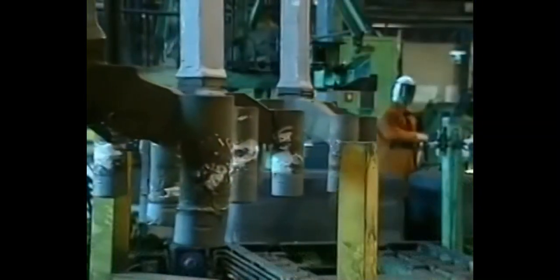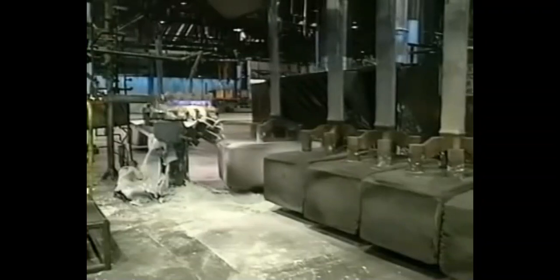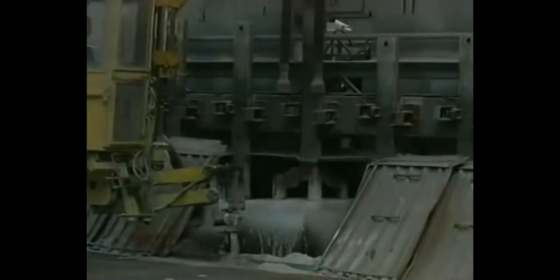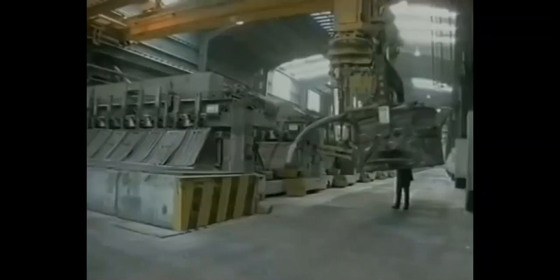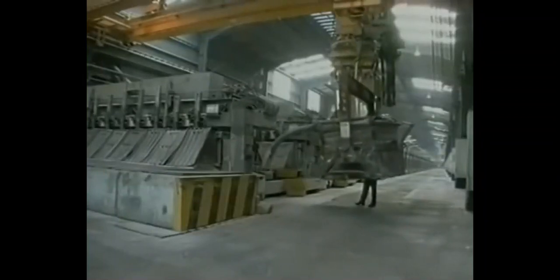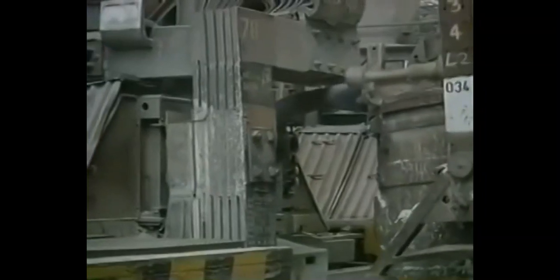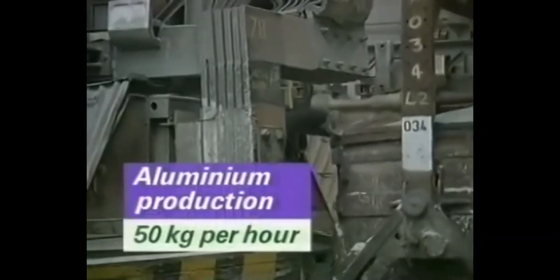The baked anodes are fitted onto steel stubs. These are held in place and connected electrically with cast iron. The anodes are sprayed with molten aluminium to protect the top and sides. Electrolysis takes place 24 hours a day, 365 days a year. A loss of power of more than a couple of hours would be disastrous, as the electrolyte and the aluminium would solidify. Liquid aluminium is sucked from the cell into a brick-lined steel crucible. Each cell produces about 50 kilograms of aluminium per hour.